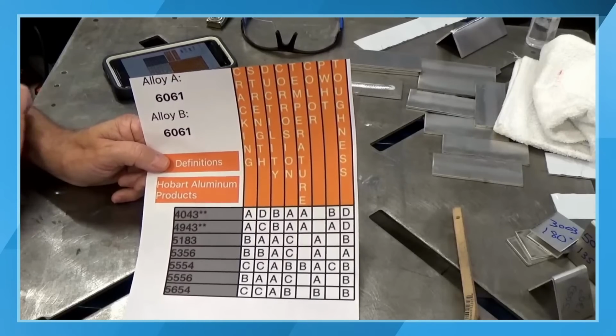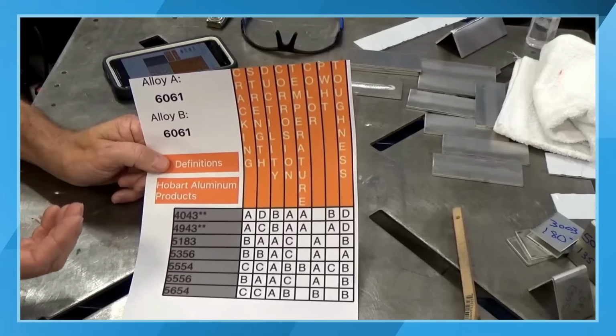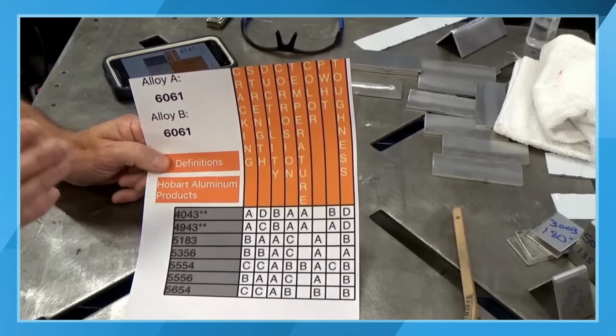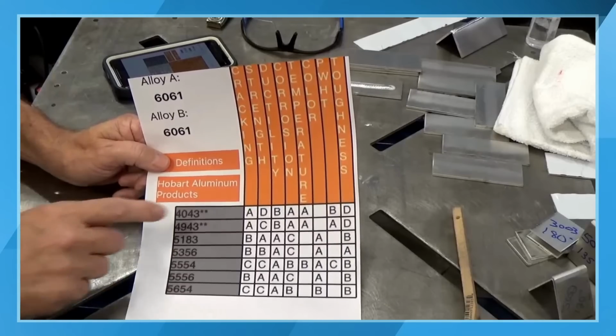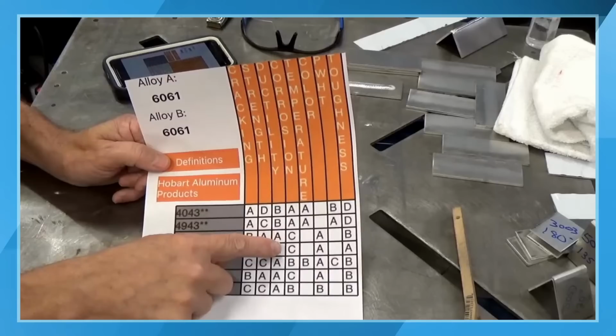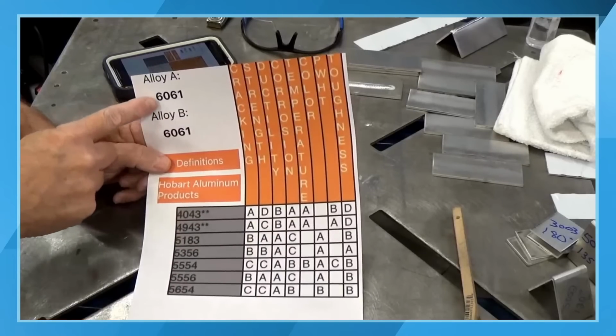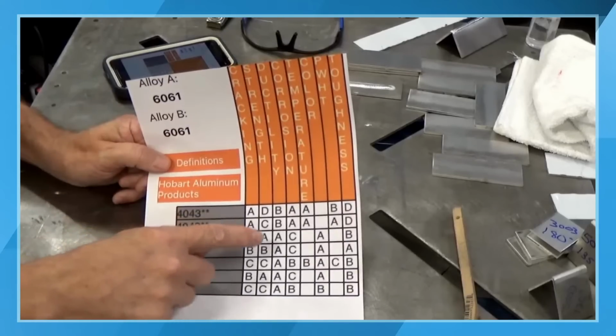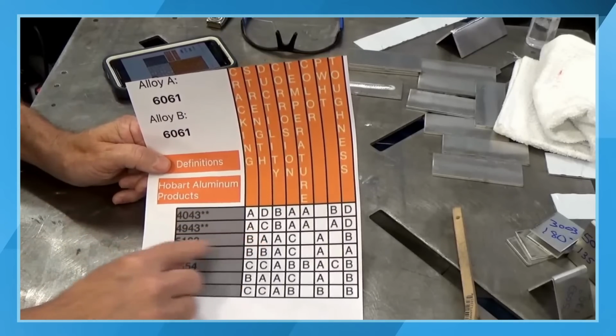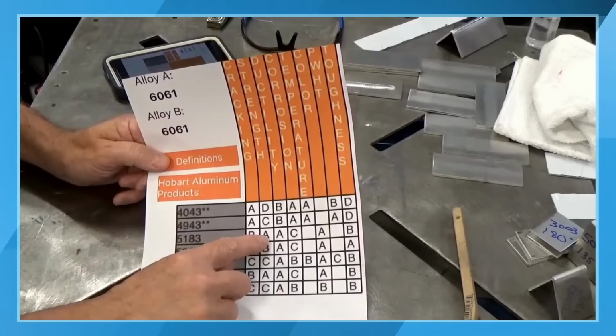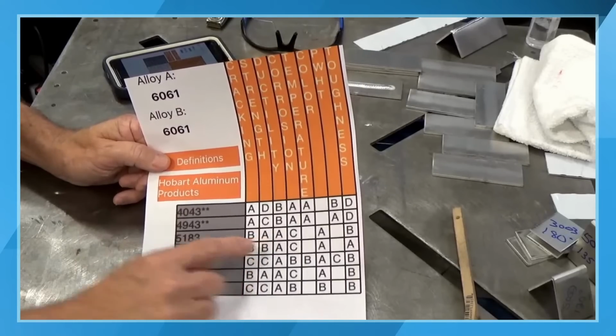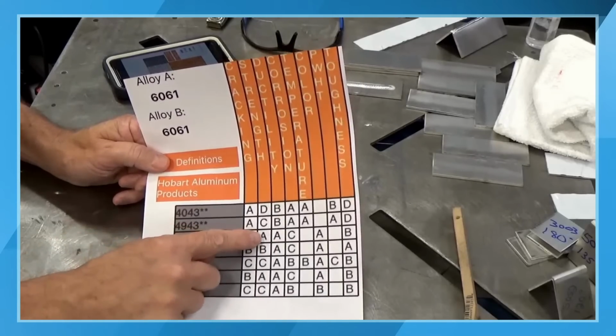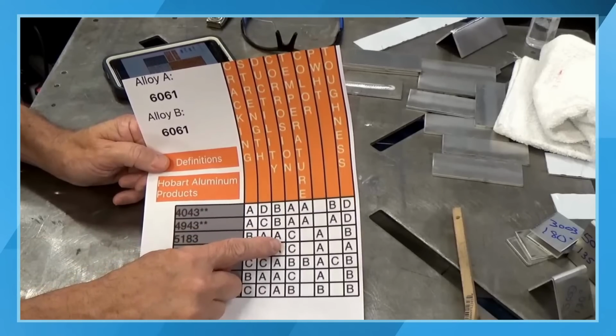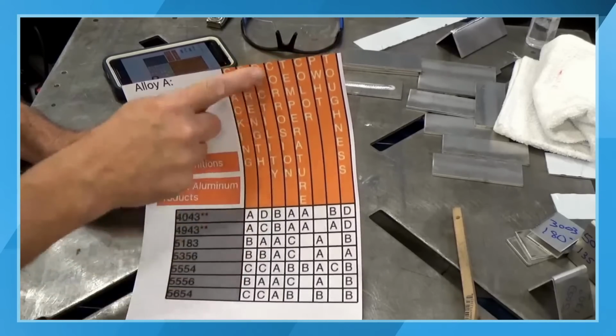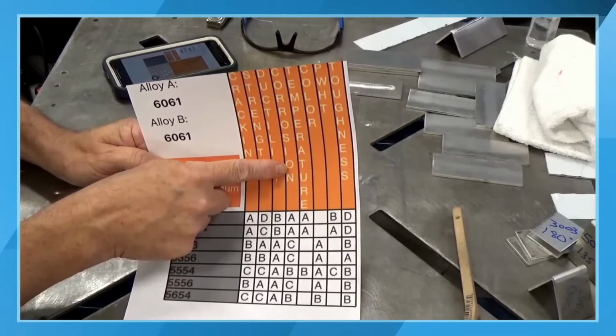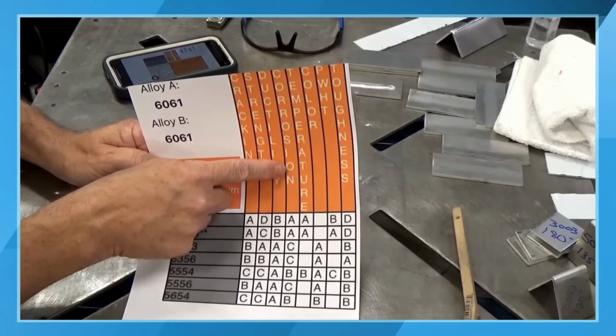So if the weld is too hard, the ductility will be less. And a lot of times, not always, but a lot of times if your strength is higher, your ductility will be a little bit lower. But with 6061 as your base metal alloy, on this particular application, that is not true for 5183 filler metal. The strength and ductility are both A. So that is an excellent filler metal of choice if you need high strength and you need the weld puddle to still be flexible.